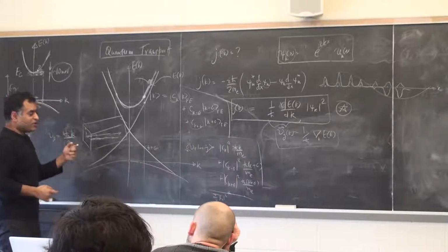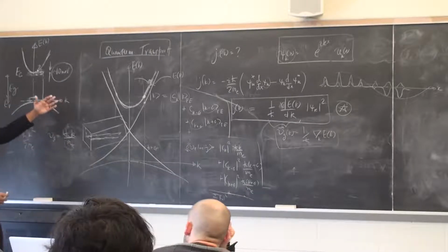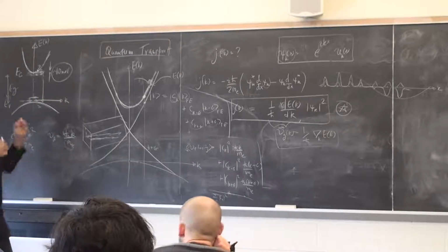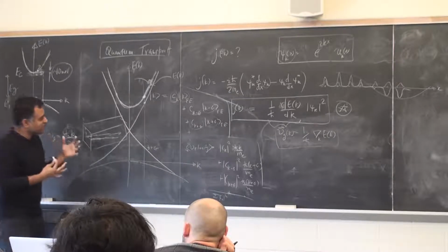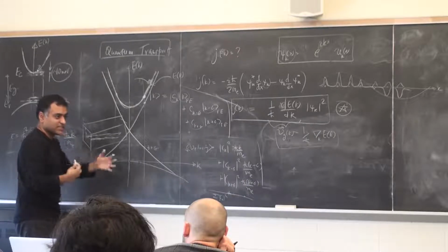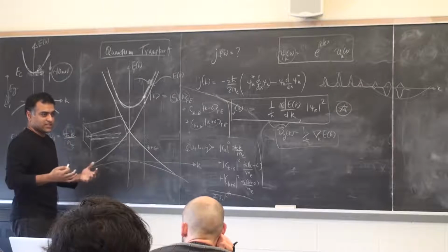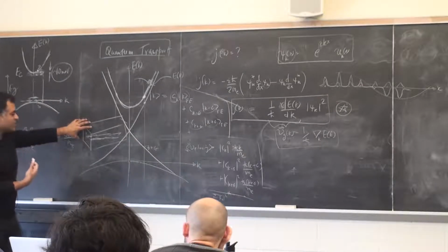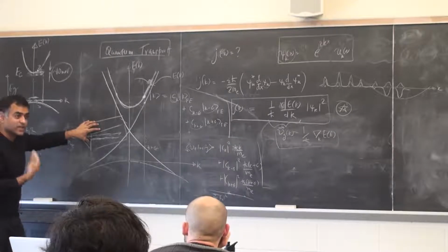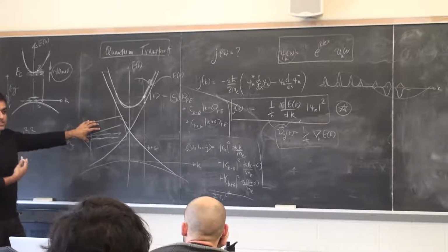So in the classical Drude model, the idea was that the origin of resistivity was the electron bumping against the atoms of the crystal and lattice, and that's why you had resistance. Here the problem is turned completely upside down. Here what we're saying is, if the crystal is perfect, you cannot have any scattering. You cannot have any resistance if you have a perfect crystal.